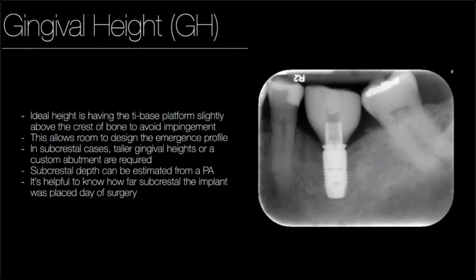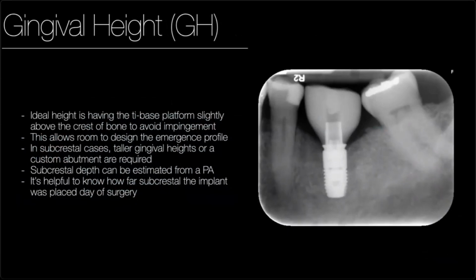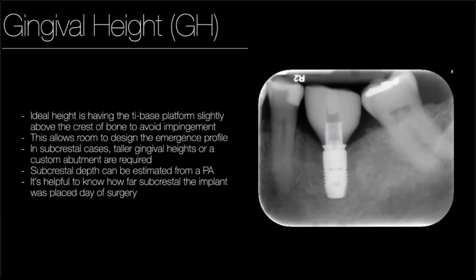So the ideal height of that Ti-base platform is just above the crestal bone. You don't want it impinging on the bone, but you want it low enough that you can develop as much of the emergence profile with the ceramic as possible. In subcrestal cases, you're going to need a taller gingival height. So if this implant was placed 2.5 millimeters subcrestally, I would have had to use a 3 millimeter tall gingival height. In this case, it was about 1 or a little less than 1 millimeter subcrestal. I used the 1 millimeter gingival height and got a nice result.